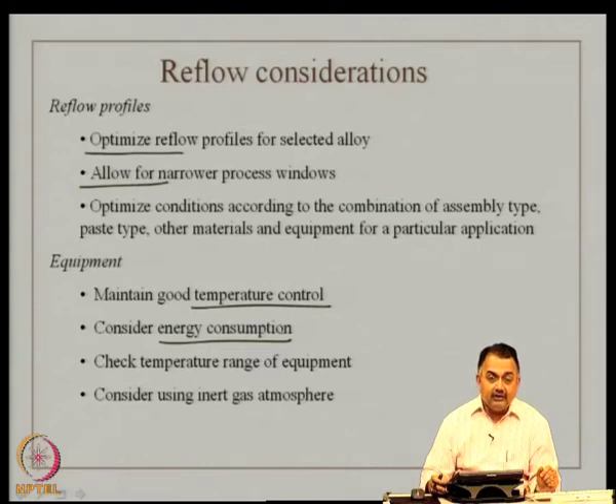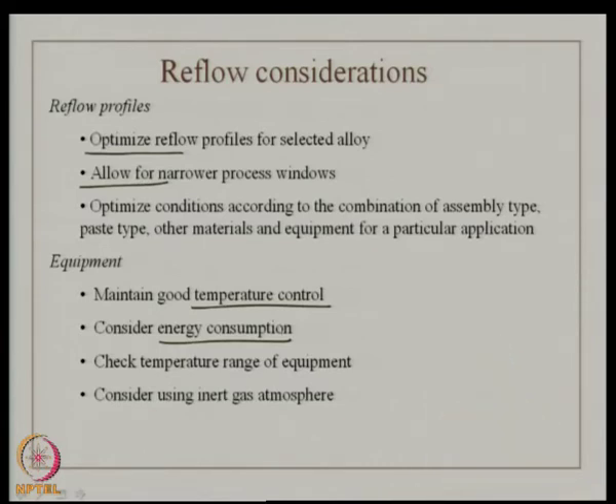Check the temperature range of equipment. Sometimes, because you have been working with lead based solder, your equipment is incompatible for lead free. So, make sure your equipment is in place and consider using inert gas atmosphere, that is nitrogen based reflow. Now, this is an option that need not work for all designs. You can consider working with inert gas atmosphere to reduce defects, but in some cases we have seen inert gas atmosphere in fact induces defects like tombstoning, skewing and so on. So, have a control on the conditions.